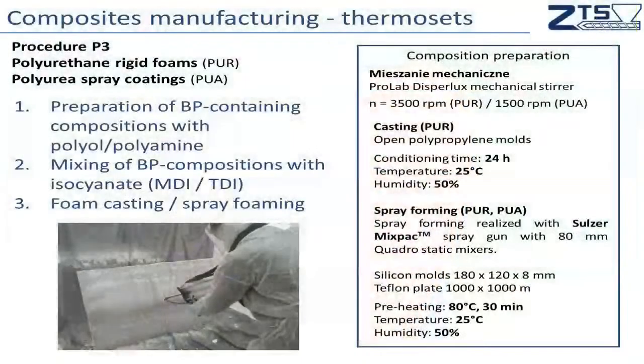In this case, we can see that we are using spray coating with a small laboratory spray gun. However, we have also realized the industrial process, and at this moment this material is applied in industrial conditions, and it is commercialized. What is quite interesting here is that in the case of all the thermosets, basalt powder seems to be reactive, but I will talk about it later.